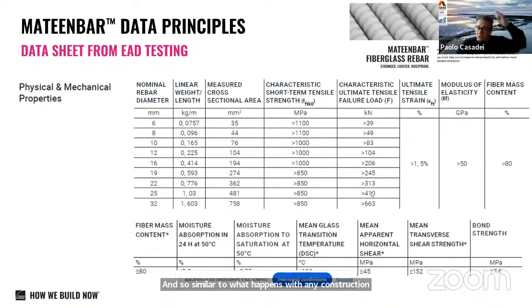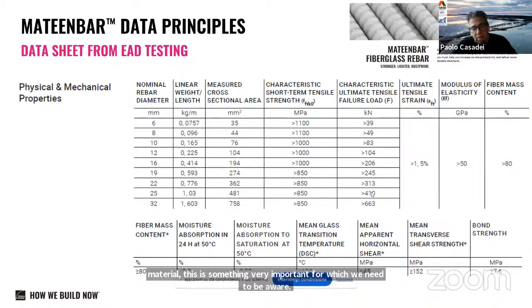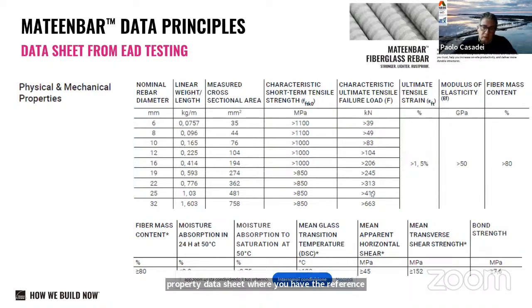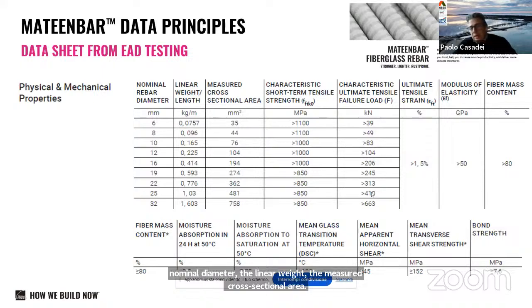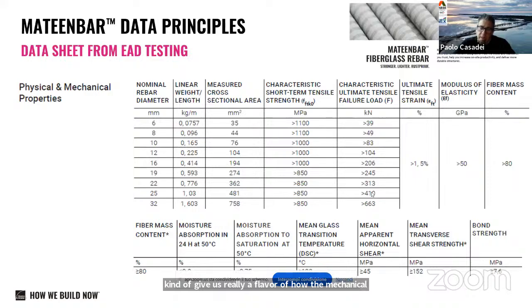And this is just a picture, very briefly, of a mechanical property data sheet where you have the reference of the nominal diameter, the linear weight, the measured cross-sectional area, characteristic tensile strength, the load, the strain, the modulus of elasticity, and also the fiber mass content, which gives us really a flavor of how the mechanical properties are obtained, and then also all the other parameters which are important for qualifying the product.